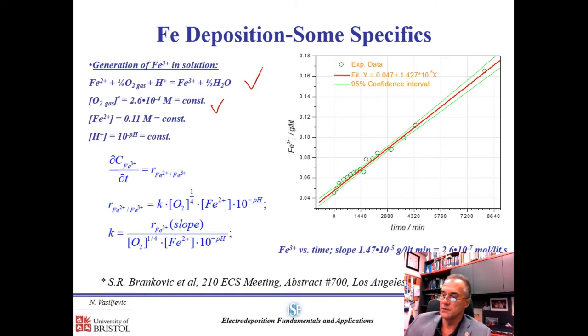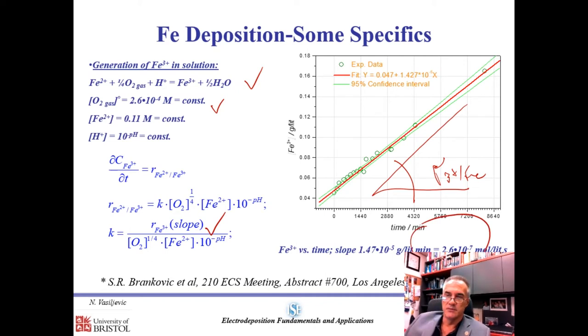And if you follow the accumulation of iron 3 as a function of time from iron 2 in the solution, you can come up with the rate of this generation, which is equal to the slope of this here, and I give you the calculation here. Why is this important? Because iron 3 forms one of the most insoluble hydroxides, and if you have too much iron 3 in your solution, stability will be compromised.